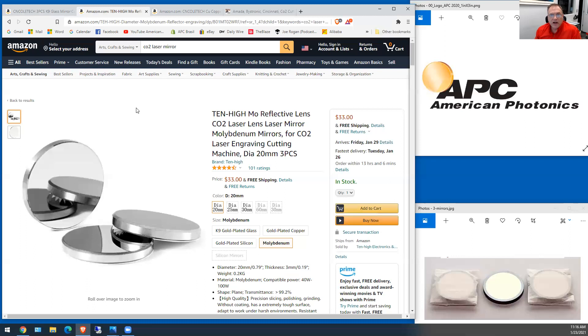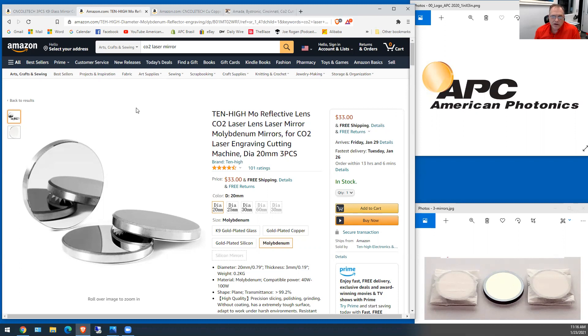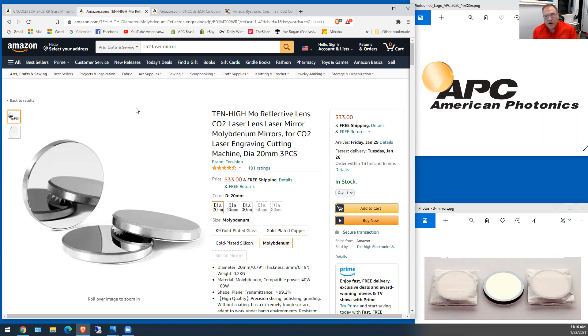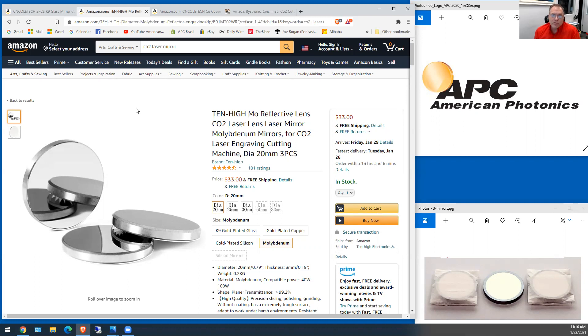then it hits the first molly mirror at 65% and then the next molly mirror is 65% and then the last molly mirror at 65% and then go through the lens which is probably going to transmit about 80% of whatever red laser is left. You're probably looking at you lose about, you have about maybe 15% of your red laser left. So molly isn't the best for transmitting that red laser.